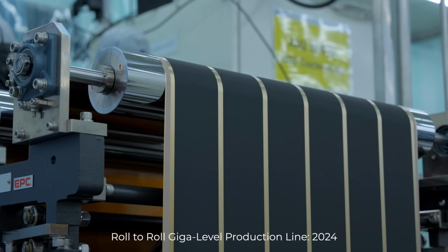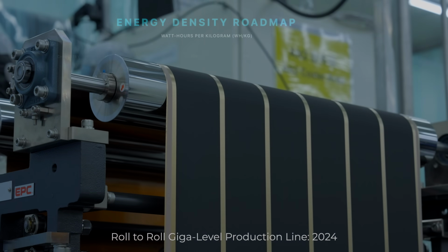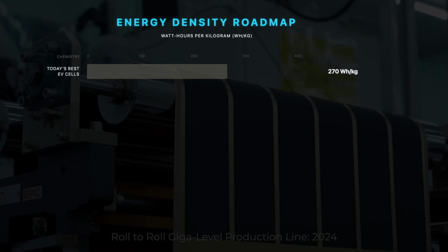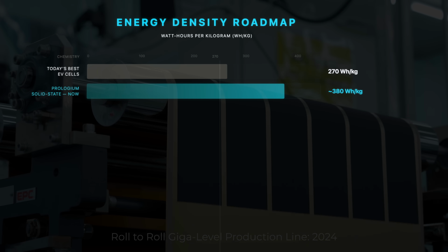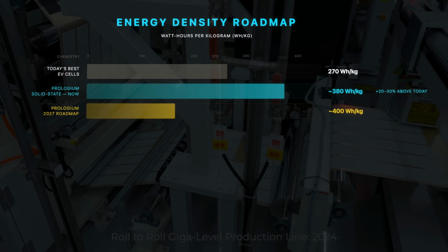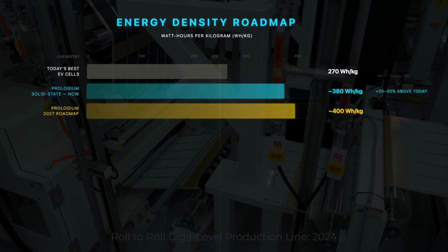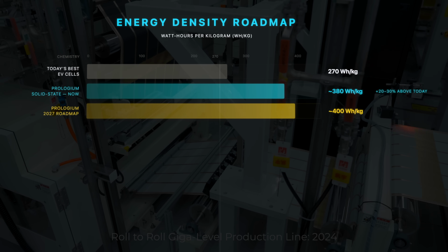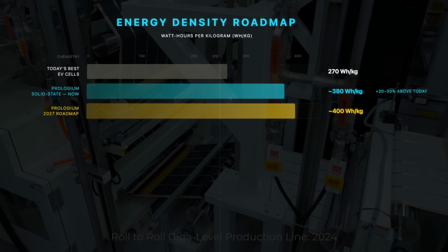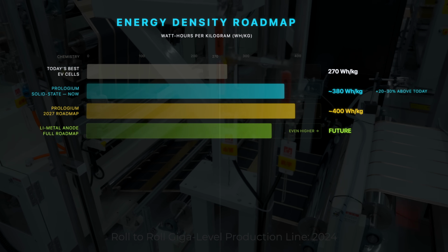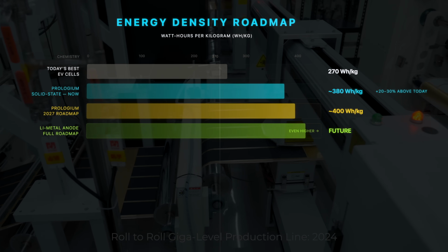For example, the best cells in EVs today are around 270 watt-hours per kilogram. ProLogium solid-state cells beat that by 20 to 30%. And the roadmap goes even further. They've already reached 380 plus watt-hours per kilogram. And it's manufacturing ready, not a lab experiment. With a full lithium metal anode on the roadmap, they could push that number even higher.